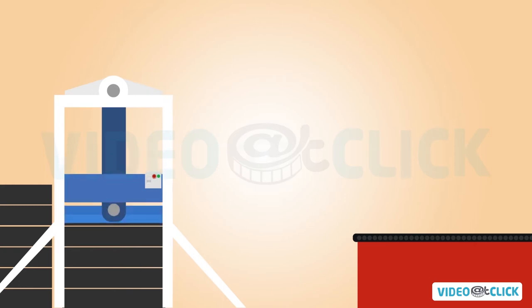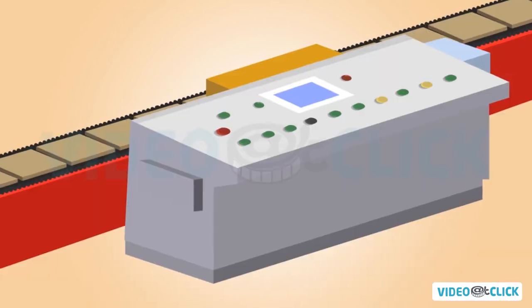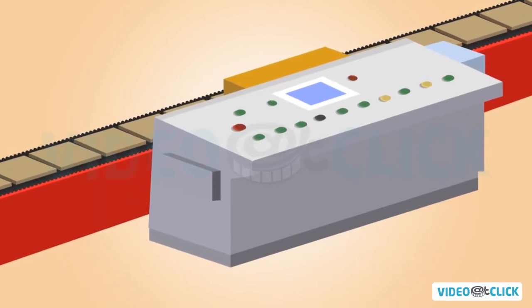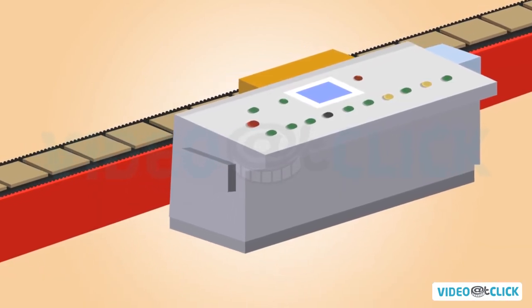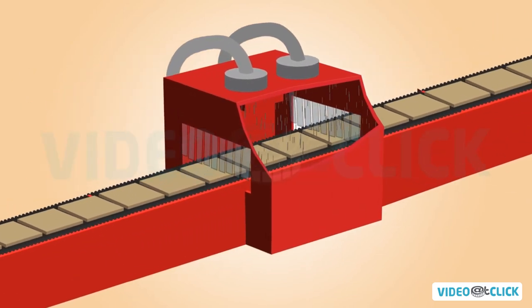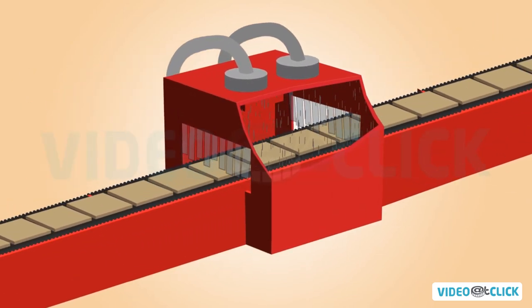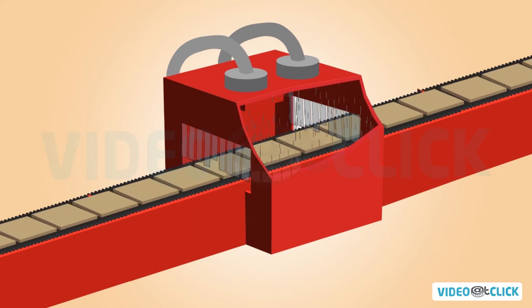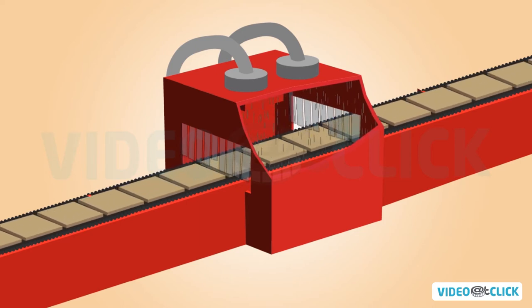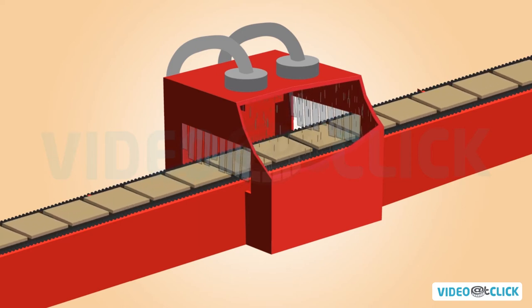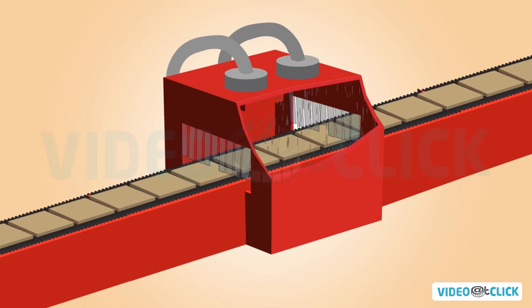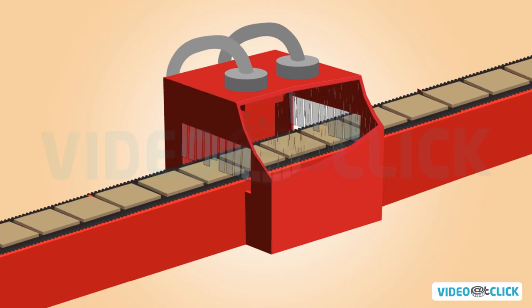Shot blasting is one of the secondary processes. Cured pressed units are fed to an enclosed chamber where small particles of steel are fired at the product as it progresses through the chamber. This abrasion creates a pitted even texture to the surface of the product and the dust and fine steel from the process is extracted, leaving a finished product by the time the unit leaves the blasting chamber. Individual products can then be gathered on pallets and packaged ready for storage in our stockyard for customers.